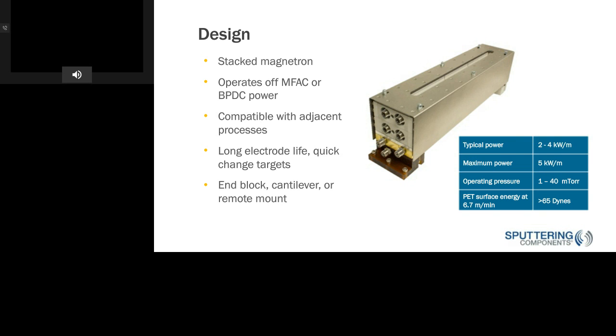A typical operating power is around 2 to 4 kilowatts per meter. The maximum power is around 5 kilowatts per meter. You'll see some slides later, we did use 7 kilowatts, and you could use higher powers if you're doing a short duty cycle, but it's best to be around these lower powers if you're doing long cycles. The operating pressure is 1 to 40 millitorr, and we've seen the best operation really between 1 and 5 millitorr. Then I'll present some of the surface energy results, but you can see that we can get greater than 65 dynes for surface energy to help with adhesion, and that's running at 6.7 meters per minute.